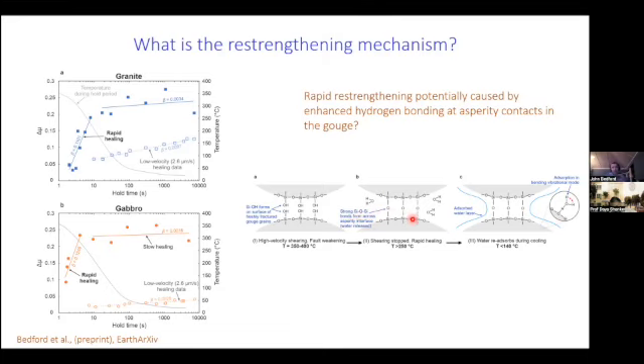bonds. And this has been studied in atomic simulations, which show that the kinetics of these reactions do increase with temperature. And it is plausible that we're getting very fast hydrogen bonding on our gouge surface at high temperature once they've stopped shearing, which is causing this rapid re-strengthening. And then once the gouge cools, we get the water absorbing in this change of vibrational mode, which is what we're picking up in the Raman spectra. And we get this change because we've got this change in bonding on the surface caused by this hydrogen bonding.